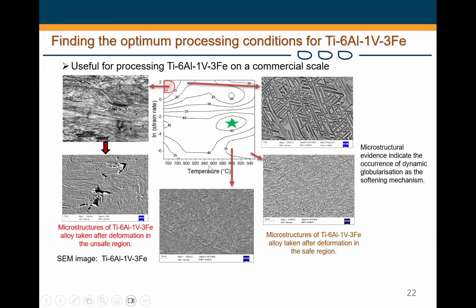Yeah. So what did we learn in that case? We were able to establish an unsafe processing window where you shouldn't ever try to deform these experimental titanium alloys. And we were also able to establish the sweet processing parameters that would allow you to go from a lamellar structure, an elongated structure, to the rounded structure. And this can then help to reduce the number of steps that you need for processing those alloys.